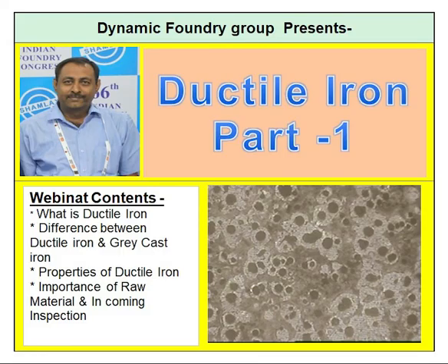Alloy elements, do not keep chromium more than 0.05, as I told you just now. Chromium more than 0.05 will give rise to carbides, and these carbides are very strong and very dense. It is very difficult even with the heat treatment. So you cannot eliminate them even after heat treatment. So try to keep chromium as low as possible.